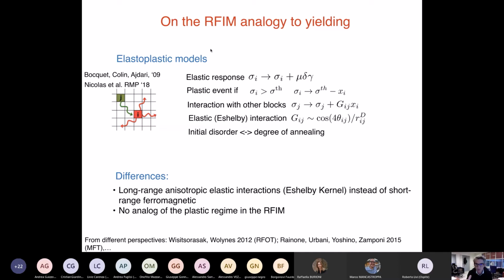If it's a broad distribution, all the sigma I in my system are very different, which corresponds to a system that has not been annealed well, and a system that has been annealed well has all the sigma I close to one another. So this is the model. Now we start from an initial condition with a certain distribution of the initial sigma I. We change delta gamma, so all the sigma I change, and then one goes above the threshold, relaxes locally, and redistributes the stress on all the others, and in this way you can have a cascade, an avalanche of changes of the sigma.